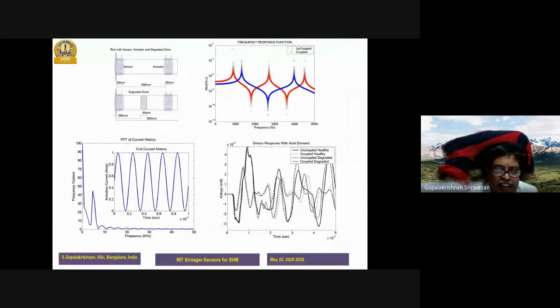And then we did a lot of numerical simulation to check how good our model is. You see the difference between the coupled and uncoupled approach, and how the uncoupled approach gives erroneous results. And this is the damage detection algorithm we use with coupled and uncoupled, and we see that it is necessary to use coupled methods to get more reliable results. I'm not going into the theoretical formulation of it. I want to keep the equations to a minimum, but I want to show that we have done this.